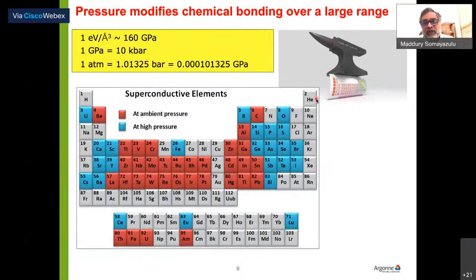Now, what does pressure do? As I told you, I'll give you a little bit of an idea about how pressure and energy are correlated. So typically, if you look at 160 GPa, which is about 1.6 megabars, if you do the conversion in the table from the top, I told you, and 1 atmosphere is 1 bar, 160 GPa is 1.6 million atmospheres. That corresponds to about 1 eV per angstrom cube. So already you're beginning to see what pressure does.